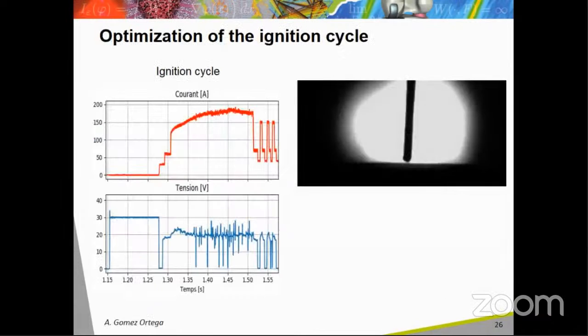This kind of defect can be reduced by improving the wetting of the liquid at the beginning of the deposit. This is possible by promoting the heating of the substrate at the beginning of the deposit using an optimized ignition cycle. By imposing a high arc intensity during the ignition cycle, small droplets are formed at the wire tip and sprayed on the surface of the substrate. These small droplets produced by a high-power electrical arc have a very high temperature and then favor the heating of the substrate surface before the beginning of the CMT cycles, corresponding to the deposit of larger or less hot droplets.